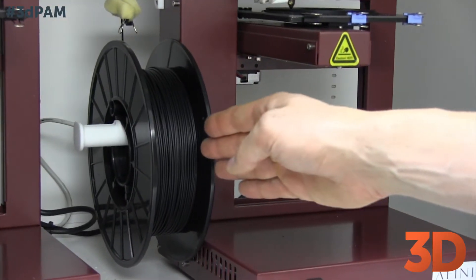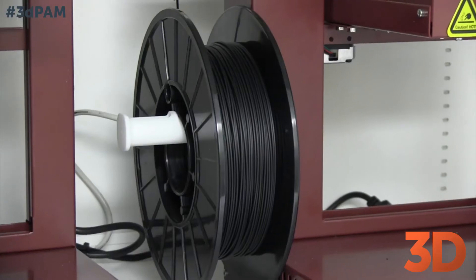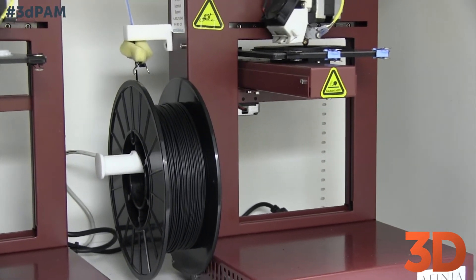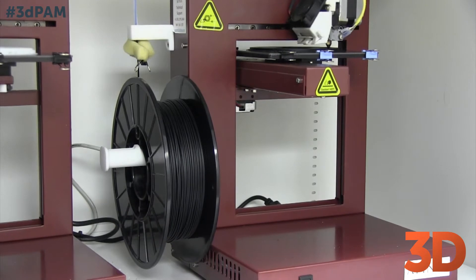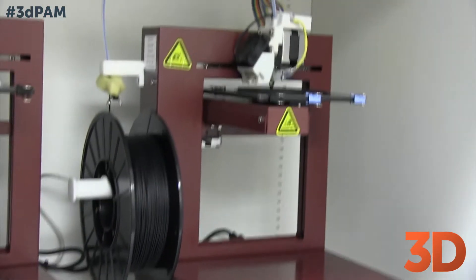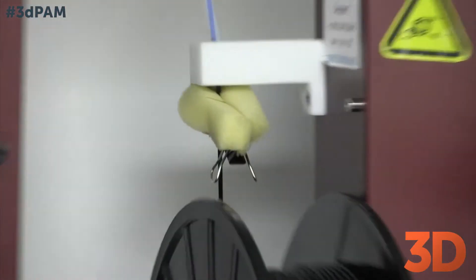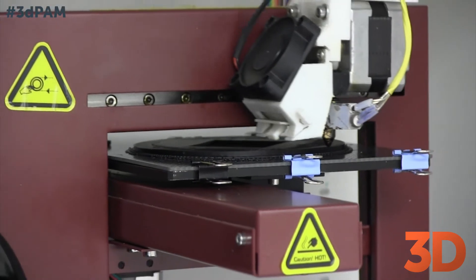What we have here is a very high quality filament — it's the premium filament from Affinia. We've noticed that the filament has a big effect on the quality of the part, not only in the part itself but also in your ability to release it from the support structure and raft. The colors we found to be most effective from the Affinia premium line have been the white and the black material. Other colors such as red and blue were more problematic in terms of being able to separate the parts from the support material, or didn't give us as nice a surface to work with.